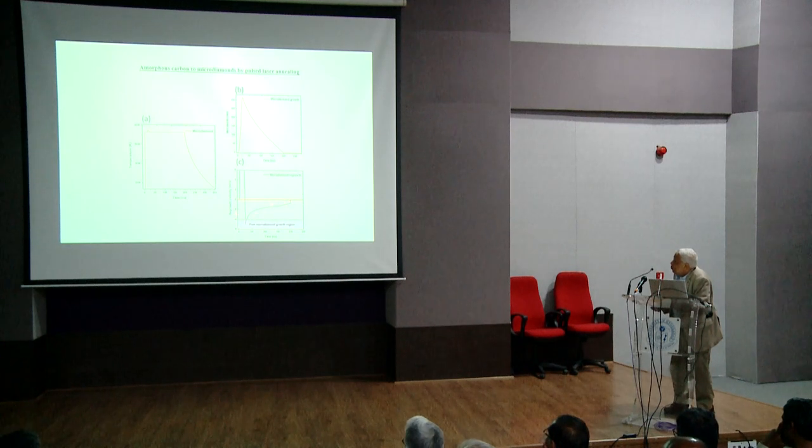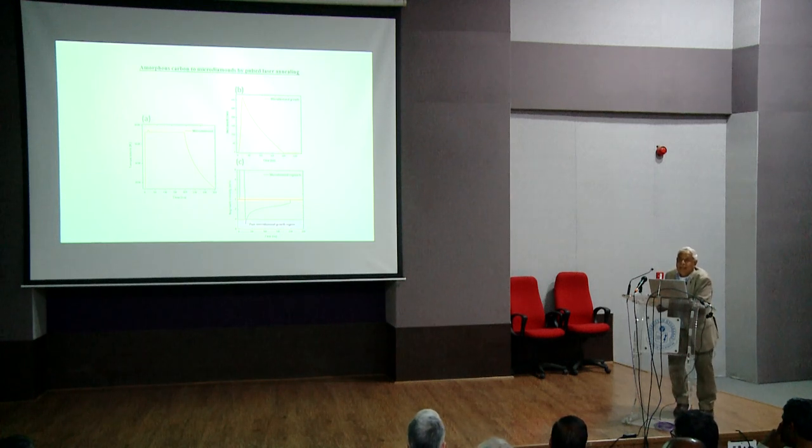You can see you are growing at the rate of 5 to 10 meters per second, making diamond. So even in 200 nanoseconds, if you put 10 meters per second growth rate, you can make a very big crystal. Microns, several microns.